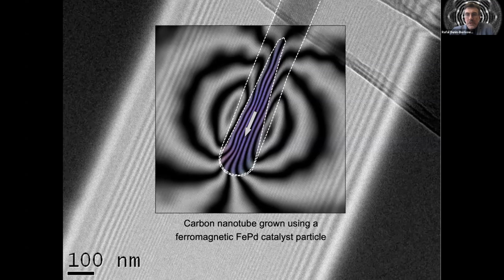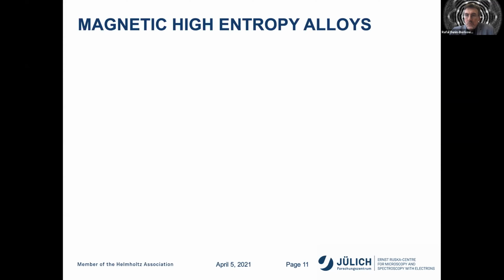So just to begin with, I'd like to illustrate why we want to image magnetic microstructure in a real material. And this is a magnetic high entropy alloy. Now, high entropy alloys are metallic alloys which are formed from near equiatomic proportions of 5 or more elements, and they have tunable magnetic properties depending on the constituents of the alloy and also on the preparation conditions, especially the annealing conditions.